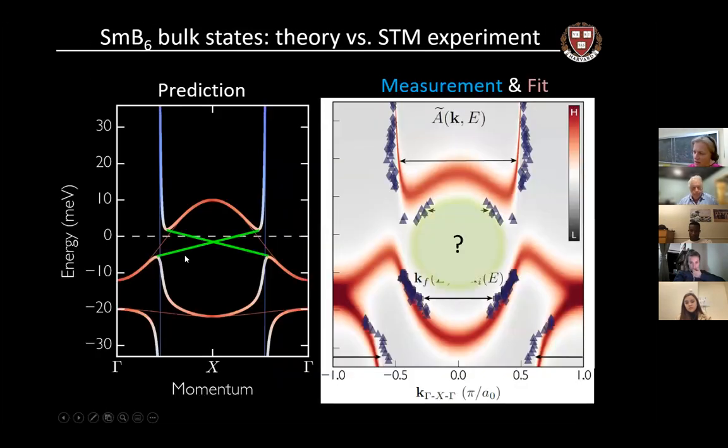And the punchline is, by looking at how the wavelength varies with the energy, we can plot wavelength. Inverse wavelength is momentum in quantum mechanics language. And energy is the voltage that we tune with our microscope. So actually, this is our independent variable. We sweep the energy as the tip sample voltage, and then we measure the wavelength, our dependent variable, but we plot it in this energy versus momentum plot, which is a standard way to plot band structure.